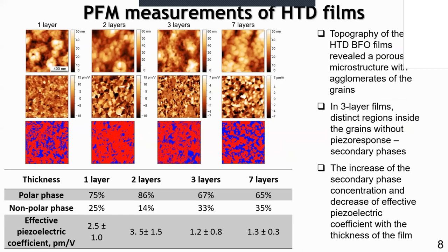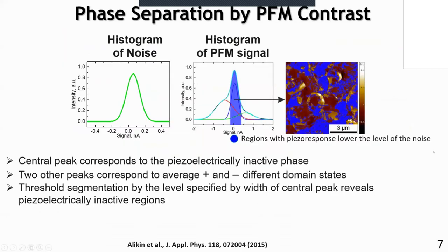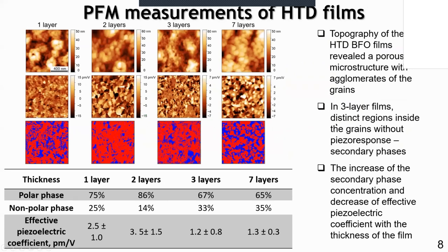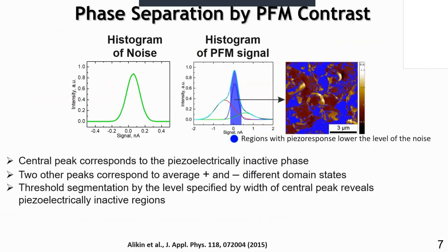So the thing is, I will start with that one again. We can estimate the noise level, and here the blue one, let me check, maybe I'm a bit confused with the colors. The blue color corresponds to the non-polar phase. Yes, I understand, but you use the piezo response image, yes? Yes, we use the piezo response image. And you only increase the contrast? No, it doesn't work like that. Actually, what we do is we switch off the AC voltage from the microscope, and we measure the noise level. With the noise level, we can do a threshold measurement. So we know the threshold of the noise, and we say below this value we have noise.